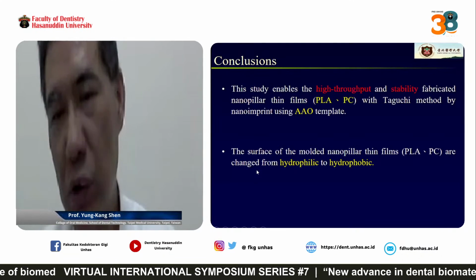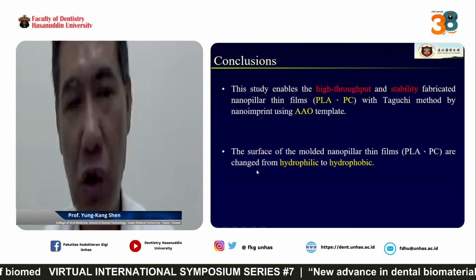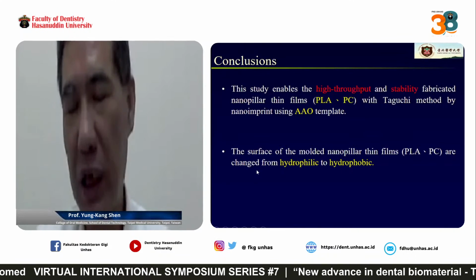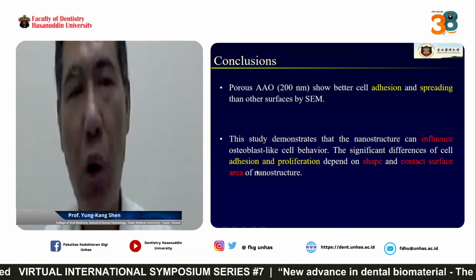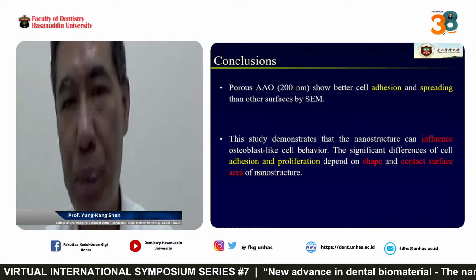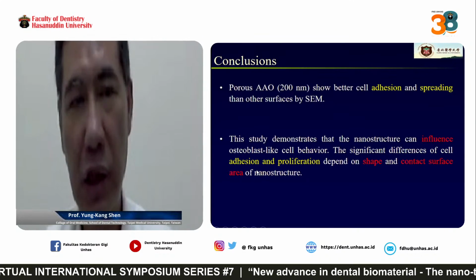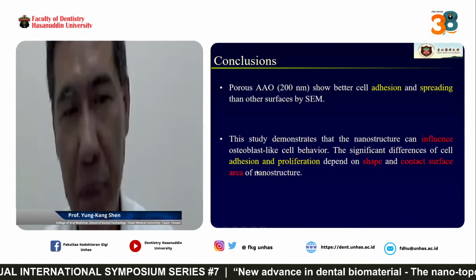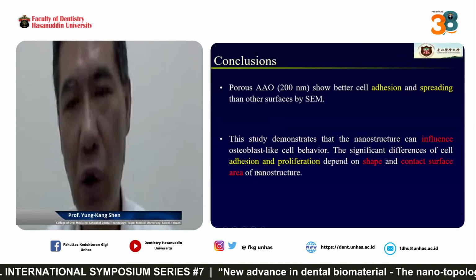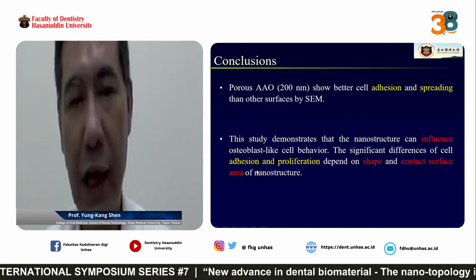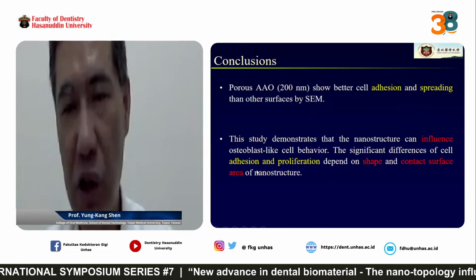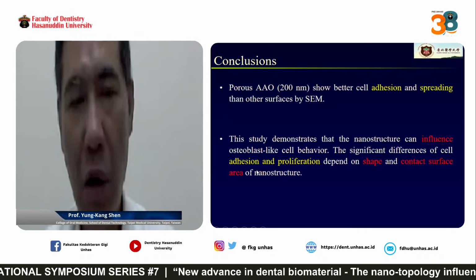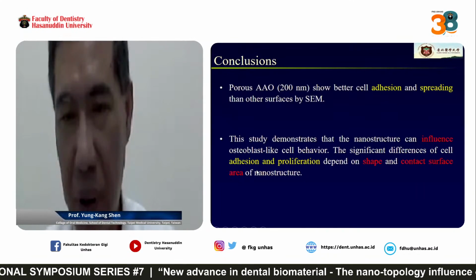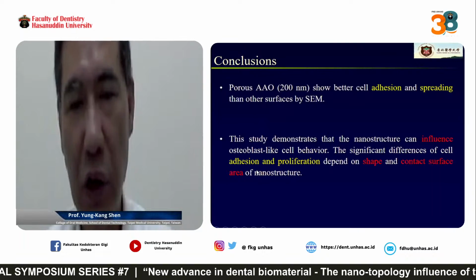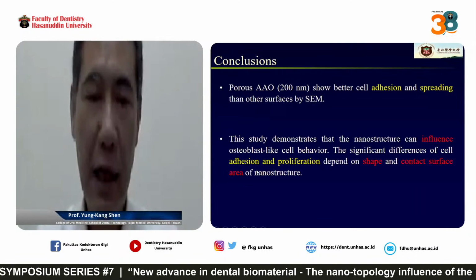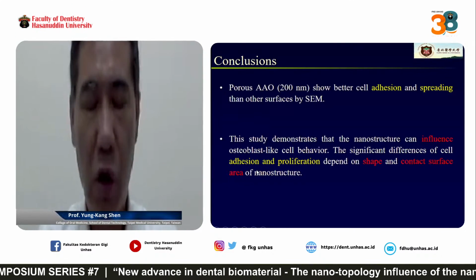For the surface of the molded nanopillar thin film, we use two types, PLA-PC, changing from hydrophilic to hydrophobic. And the porous AAO 200 nanometer shows better cell adhesion and spreading than other surfaces by SEM. This study demonstrates that the nanostructure can influence osteoblast cell behavior. The difference in cell adhesion and proliferation depends on the shape and the contact surface area of the nanostructure. So I will talk about the other topic.